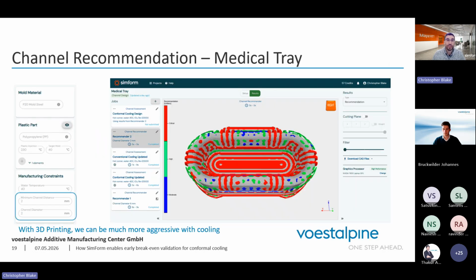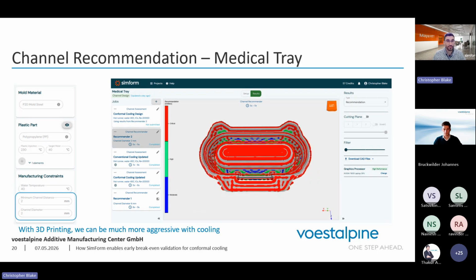Well, if we consider 3D printing as our manufacturing technique for the cavity and core inserts, we can be much more aggressive with our cooling strategy. So here we can really tighten the manufacturing constraints, in this case to a 2mm channel offset and a 2mm channel diameter. So this drops the expected cooling time to 5 seconds. And it essentially is telling us that we ought to try and surround the part completely with water, bearing in mind, of course, where we're going to need to put our hot runner hot tip and any ejector pins in order to push the plastic part off of the mold. And here's what it looks like on the underside.